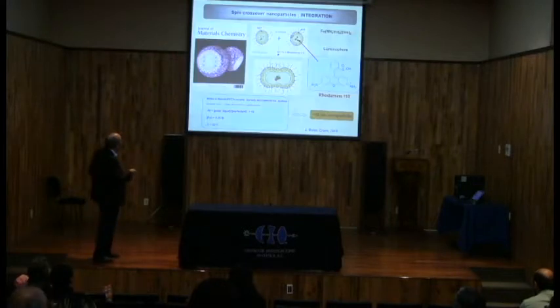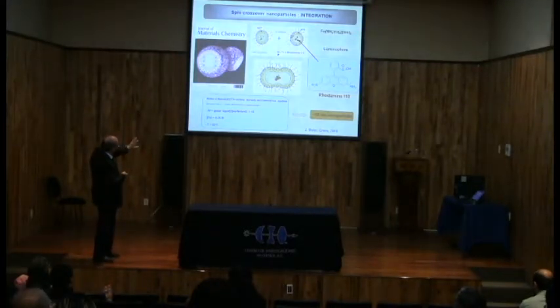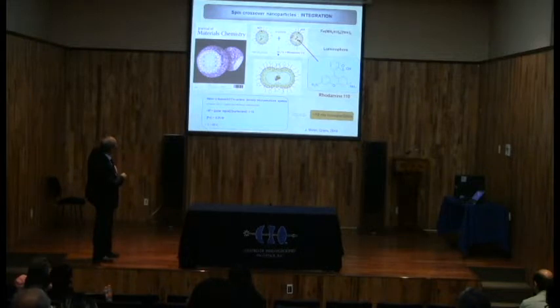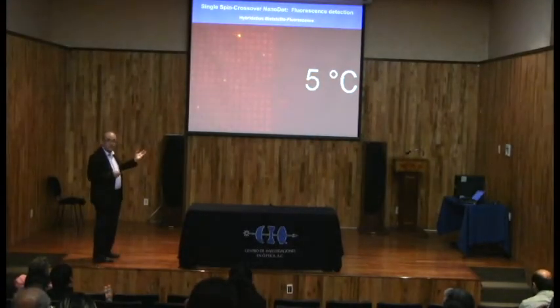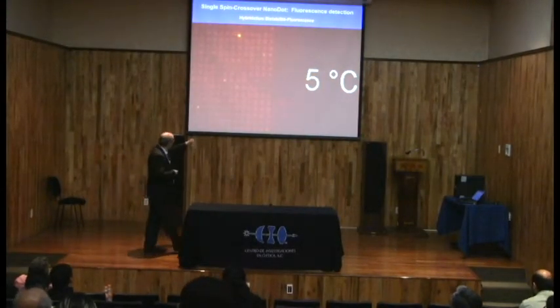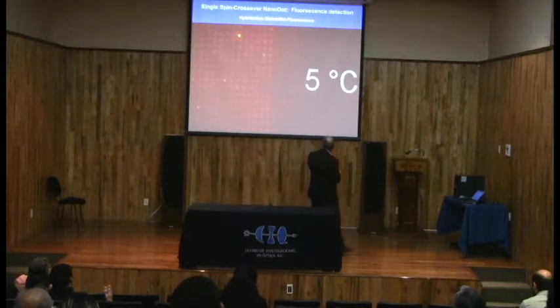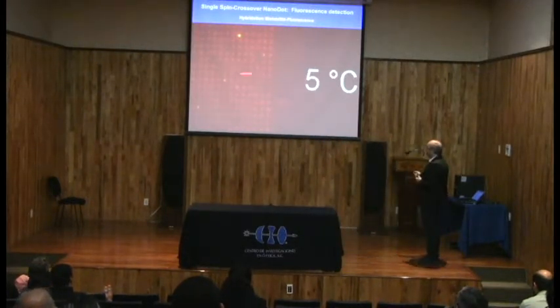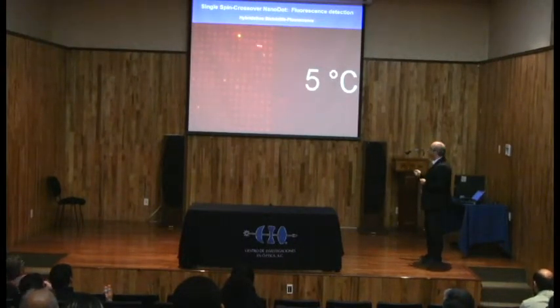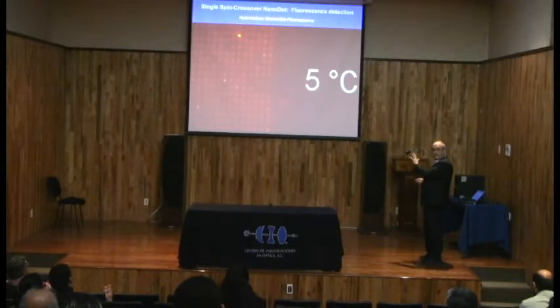Okay? So then we did these experiments here. The same protocol, we added the rhodamine in the nanoparticle in order to use this phenomenon. So Lionel got 10 nanometer nanoparticles of such hybrid systems, and then we did the experiments. We took exactly the same dose like before, but in this case we have the rhodamine in the dots. You see here we are at 5 degrees Celsius. The system is in the low spin. It's nearly dark, so the light here is absorbed. Spin crossover is around 50 degrees here.